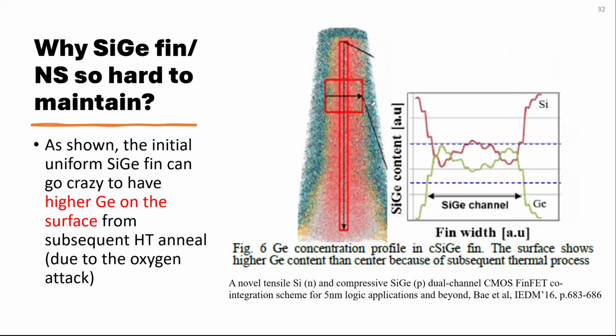It turns out IBM found out the germanium concentration for a very tall SiGe, this is a thin SiGe, if you're going through some kind of high temperature anneal, and there's oxygen inside, what happens? You look at this, the edge here becomes higher germanium content versus the center. The center is what you already have, right? You say you have 30%. Okay, you have 30%, you grow it.